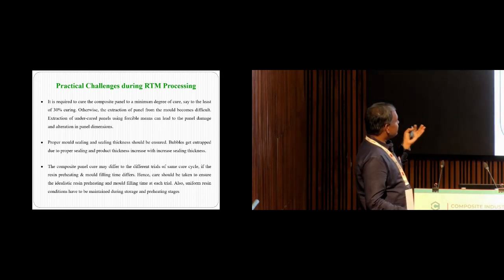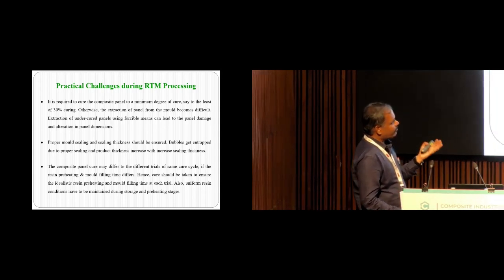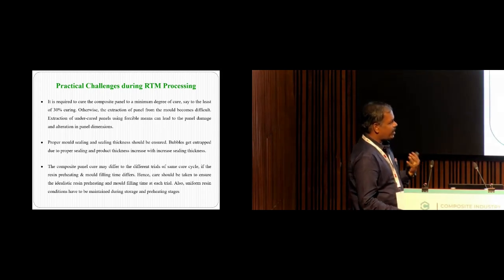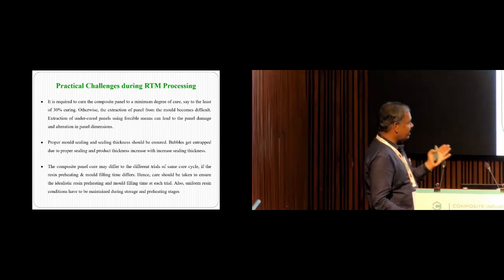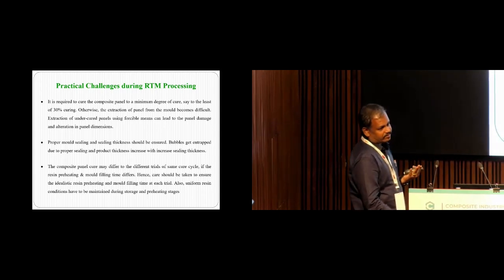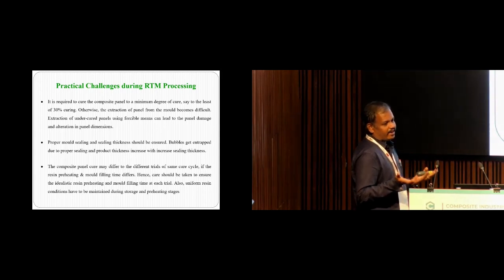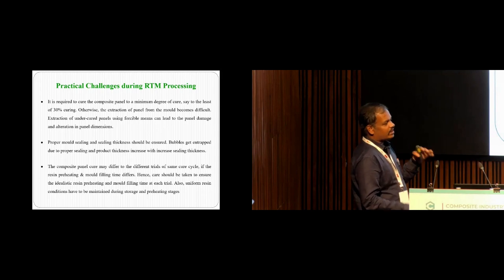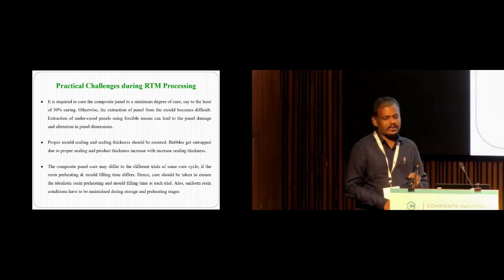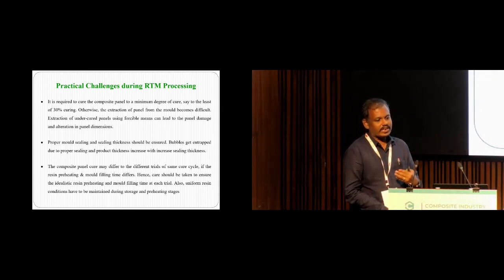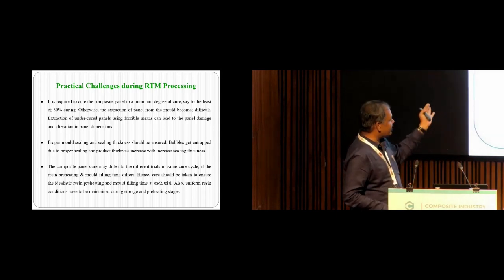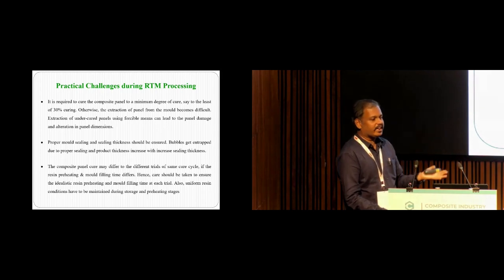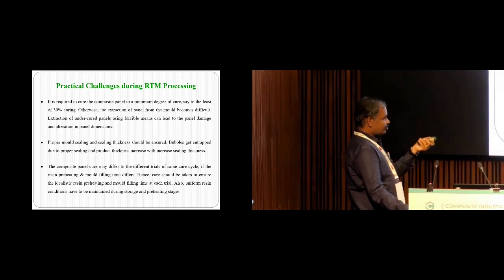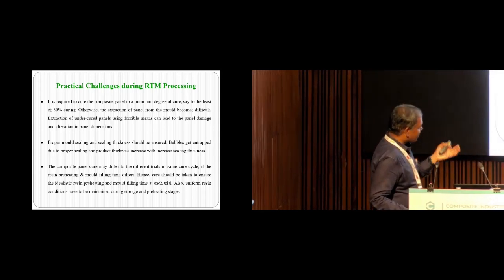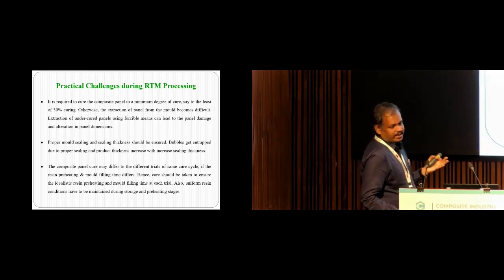The next one is that the composite panel cure may differ across different trials of the same cure cycle, if resin preheating and mold filling time differ. So you should standardize everything. If I conduct the same cure cycle first time, second time, you can have a differential composite panel cure, because there may be differences in resin preheating time. Hence, care should be taken to ensure the ideal resin preheating and mold filling time at each trial.